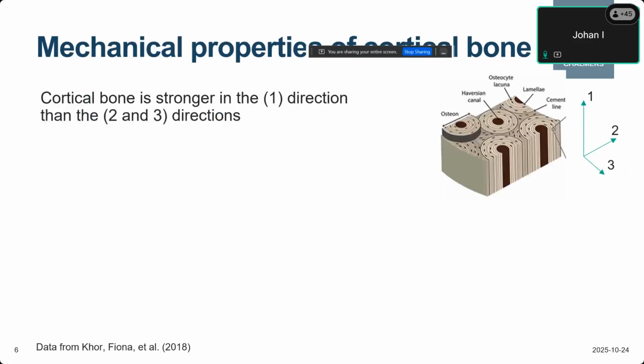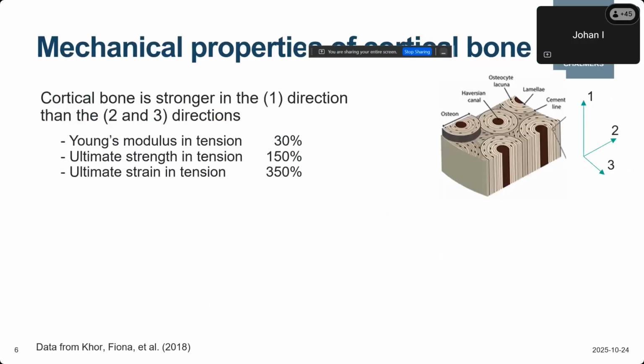If we then continue to look at the mechanical properties of the cortical bone, what we see from mechanical testing is that cortical bone is stronger in the one direction along the osteons than perpendicular to the osteon direction. The Young's modulus, and this is a mix from different types of bone, mainly femur I think, is about 30% higher in the one direction compared to the others. Ultimate strength is 150% higher. So it's much stronger in the one direction compared to the 2 and 3 directions. And the ultimate strain is also much higher. So it's more brittle, and it can withstand a much smaller strain in the 2 and 3 directions.